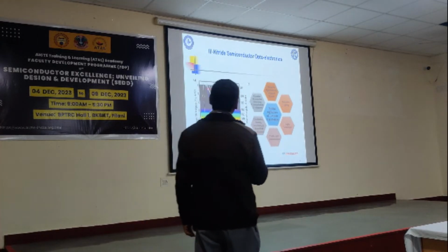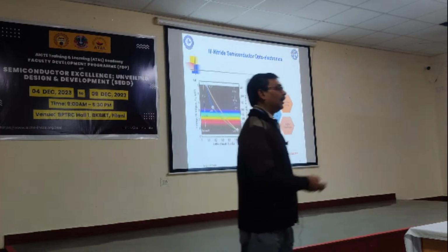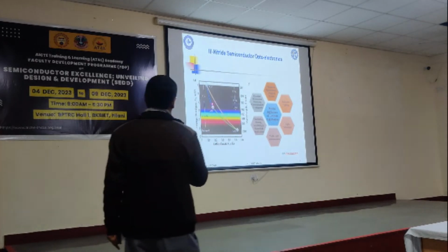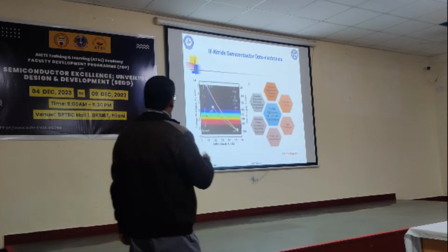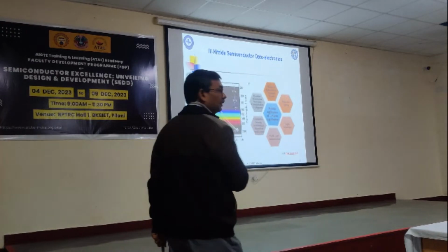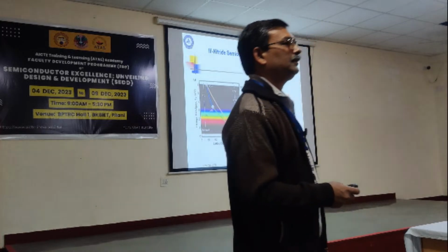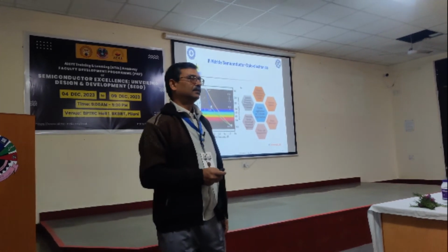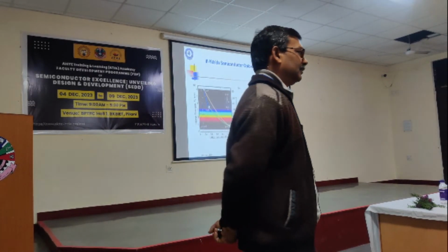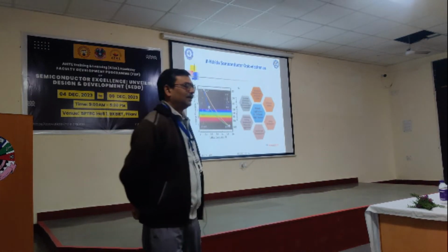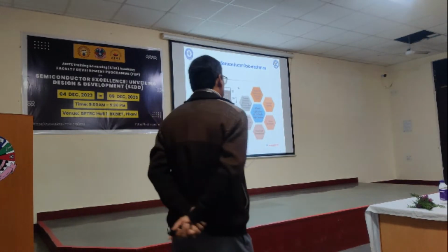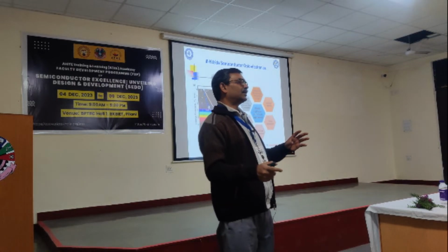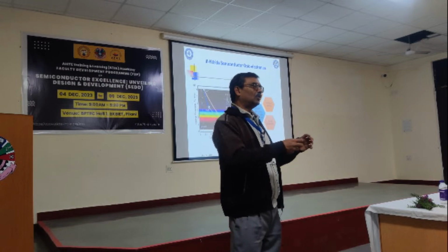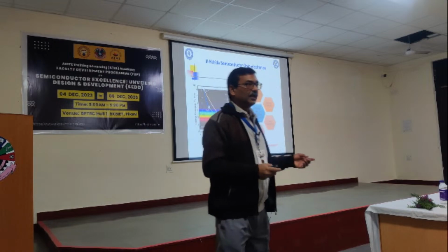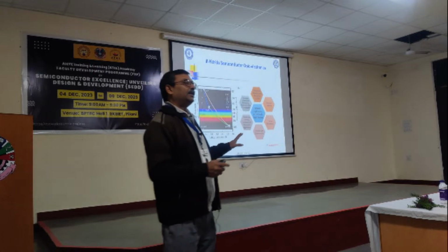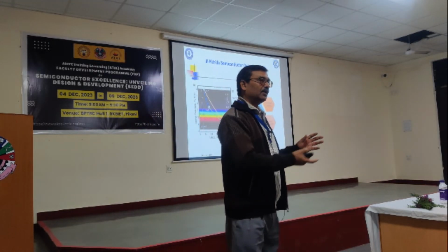Where gallium is 0 and aluminum is 100% composition, it will again be a binary composition, aluminum nitride. Otherwise, it is a certain composition, Al x Ga 1 minus x N. If the band gap is near about 6 electron volts, normally it is an insulator. So how do we categorize aluminum nitride? Is it a semiconductor? Somewhere in some books it is mentioned that if the band gap is more than 5 electron volts, or somewhere 4, somewhere 6. But with this composition, generally it can be considered a semiconductor with high band gap.